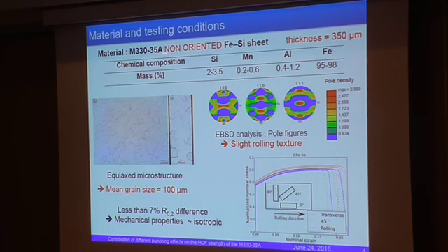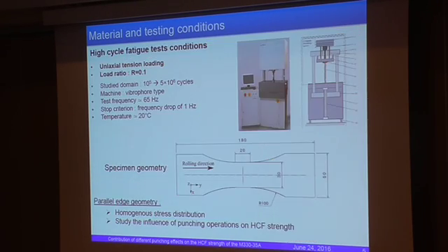So, the material is a non-oriented iron silicon electrical steel. They are rolled sheets with a thickness of 350 microns. So they have a slight rolling texture. There is about 3% silicon in it. So we get this kind of equiaxed microstructure with pretty large ferrite grains. And so we get a very ductile steel here. If we look at quasi-static properties, we can say our material is more or less isotropic. And so we perform fatigue tests under uniaxial tension.